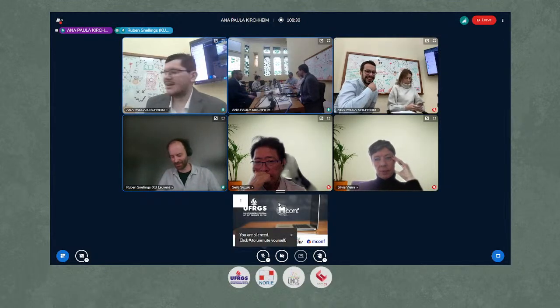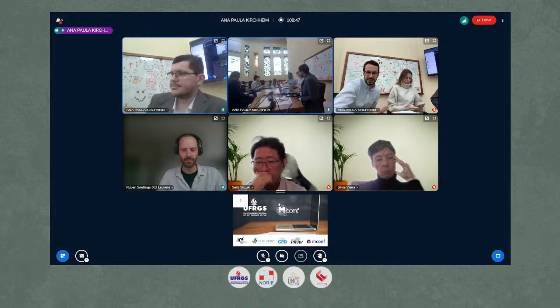Paulo wants to speak a little bit. I would agree with that, but maybe there can be a better way to find it. Sorry for interrupting, but we often come back to this discussion because the optimal sulfate content will depend on to what age you want to optimize. So for the 1 day range, 3 days range, 28 days range, and now the temperature variation that you mentioned. So the actual ASTM method using the total heat varies depending on what age you want to optimize.